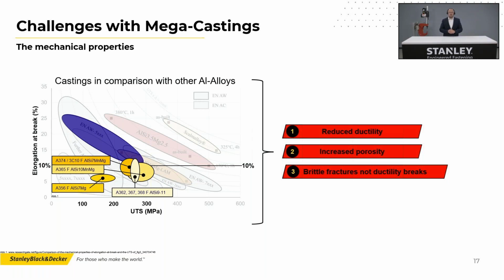In here, you can see a 10% line, and this is some kind of magic line, let's say, because a lot of people talk about, when you talk about SPR, is it above 10% elongation or is it below 10% elongation? So you can often hear the rule like, oh, if you are below, you cannot use SPR. Is this really the case? We will see. But just to sum up this slide, we have a reduced ductility, we have an increased porosity, and we have the situation of brittle fractures and not ductile cracks.